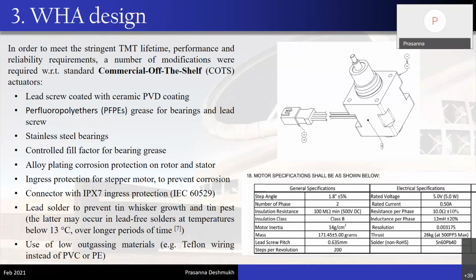tested it. When we started this test, which is a lifetime test of around 50 days, on the second day itself the entire test failed, because we were observing multiple failures, both in the actuator as well as the leaf springs. Hence, corrective actions were taken, and the leaf springs were individually developed further to have better reliability, and that testing happened in parallel. Whereas the actuator required a lot of improvements, and those improvements are listed out here.